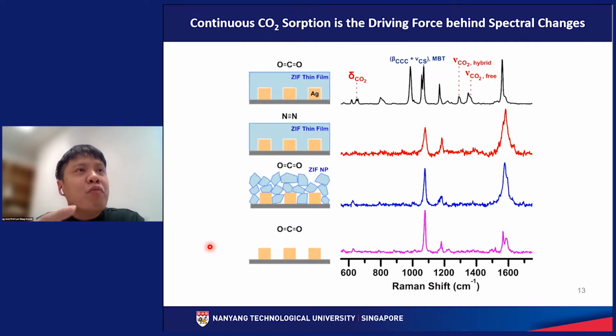Next, we try to compare with various control platforms to affirm that the continuous CO2 absorption is the driving force behind spectral changes. In the case of the ZIF thin film with the flow of carbon dioxide, we can see obvious spectral change to various parts of our spectrum. If we flow nitrogen in the presence of the thin film, there is not much change.